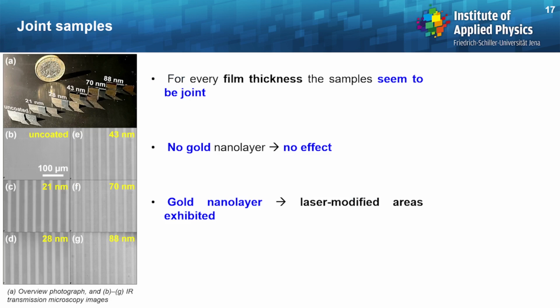The first results are quite recent. As you can see here on this photo, for every film thickness, the samples seem to be joined. However, when you take a closer look with infrared microscopy, you can see that when there is no gold nanolayer here in B, the laser has simply no effect. In stark contrast, when you have some gold nanolayer deposited at the interface, then one can see the laser tracks clearly as the dark features here on this figure.